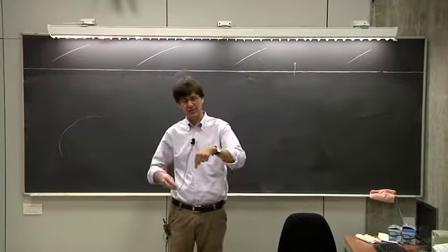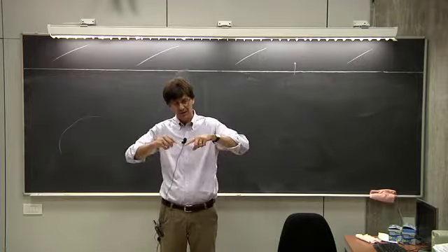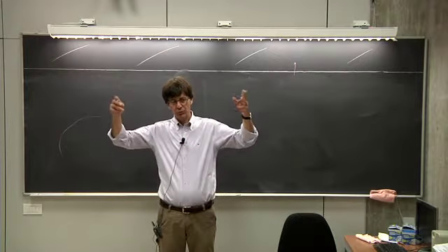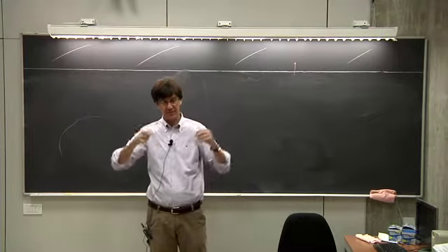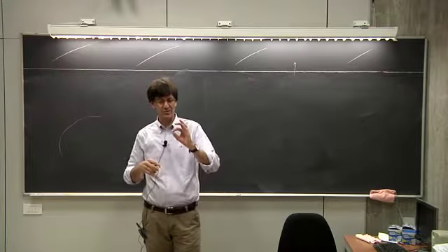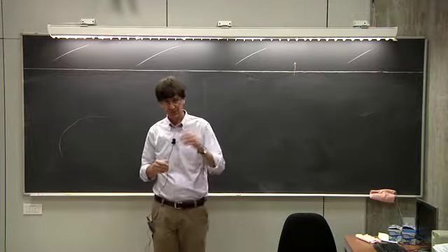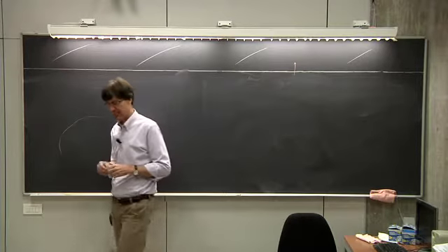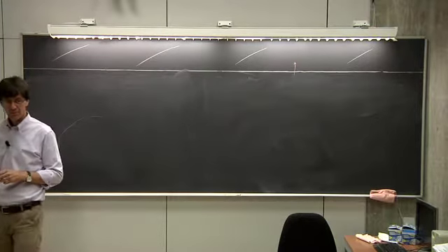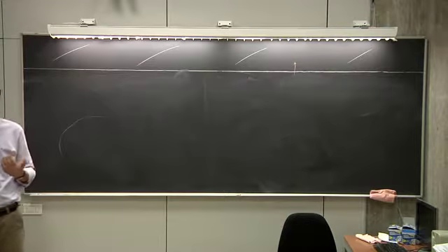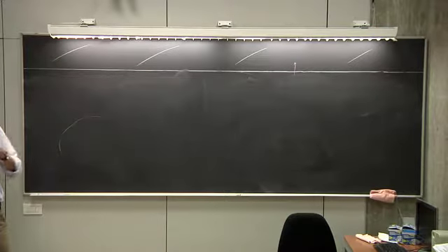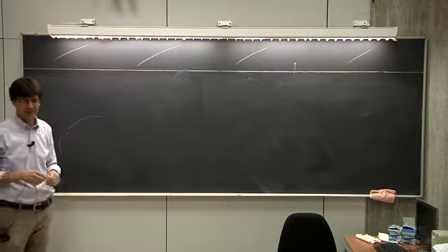If you're exciting this electron deep inside the sample, it has to be able to reach the surface and then be emitted. So if you're really close to the edge, probably the scattering will prevent the electron from being emitted outside the sample. So you don't want to be really close to the threshold. You want to be much above the threshold in order to be able to measure your kinetic energy properly.